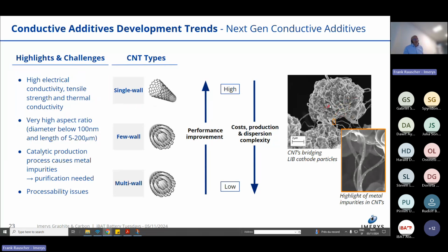CNTs, why are they attractive? You see that here on the right-hand side in the electron microscope image. You basically can consider them as wires that connect the particles in the cathode or in the anode, and with that, of course, provide excellent pathways for electrons. So when it comes to electrical conductivity, nothing is better than carbon nanotubes. And the smaller the diameter of the carbon nanotubes, going all the way to single wall, the higher the conductivity. They have a very high aspect ratio as well. The higher the aspect ratio, the more functionality they can provide in theory. But of course, it's very, very difficult to process them and get them into a matrix.